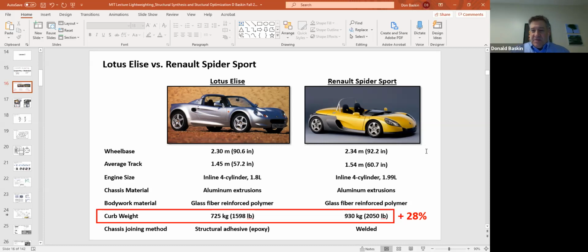Okay, but here's the big difference. Whereas the Renault weighed over 2,000 pounds, the Lotus weighed about 1,600 pounds. So 28% difference, huge difference, and that can't be accounted for by the difference in the footprint, the wheelbase times the average track. So what happened? What's the difference? The big difference is that the Lotus was bonded together using structural adhesive, it's an epoxy, whereas the Renault was actually welded together.